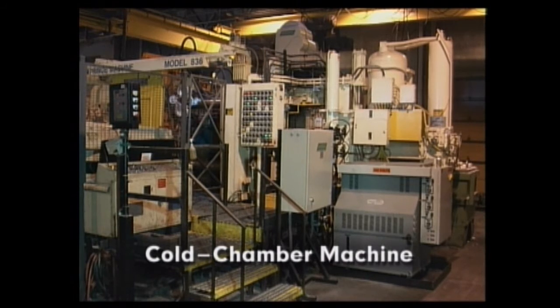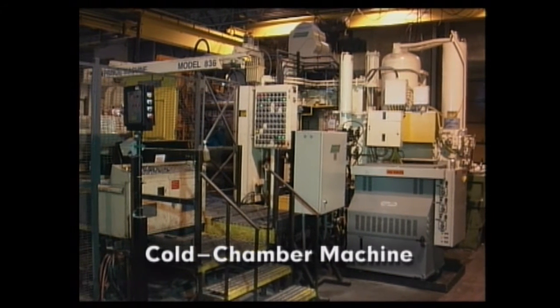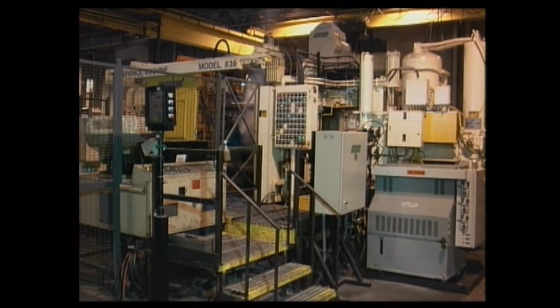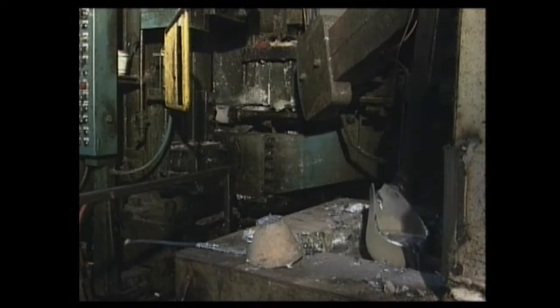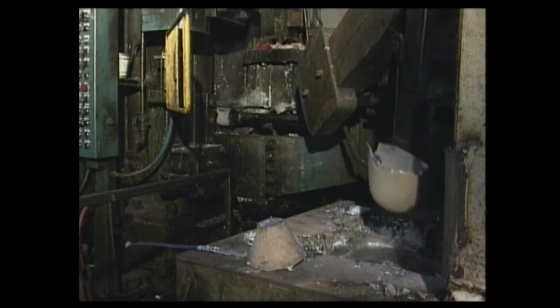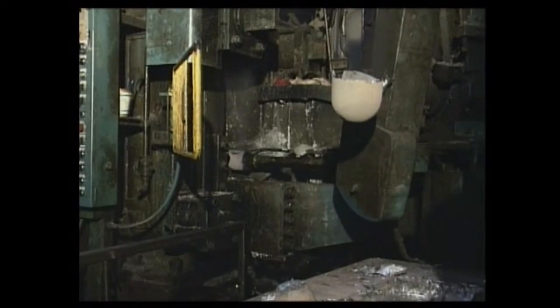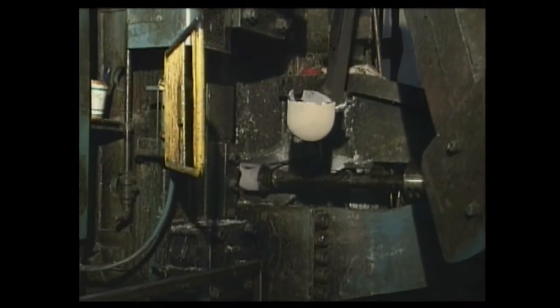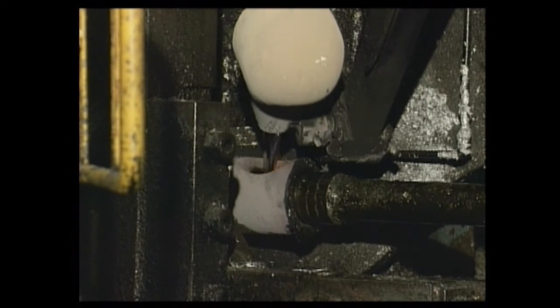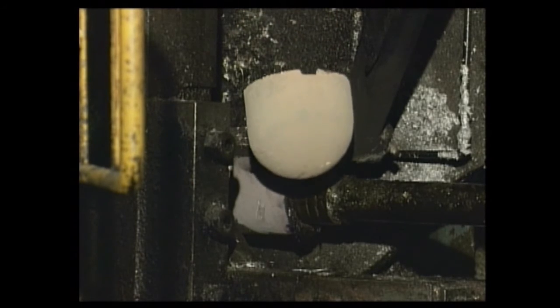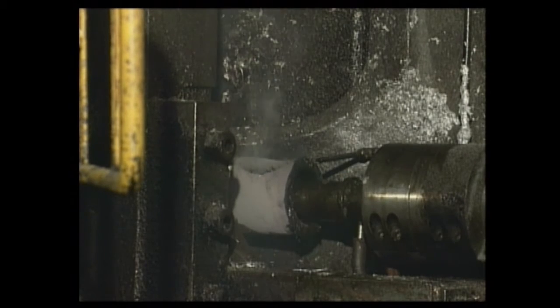The cold chamber machine is used primarily to die cast the aluminum, magnesium, and copper alloys. In the cold chamber machine, the charge is supplied by ladle or feed system from an external furnace source to a holding pot at the shot end of the machine. The feed system components are not submerged in the molten metal. The charge is poured ahead of the plunger tip through a pour hole in the shot sleeve. As the plunger advances, it closes the pour hole and drives the molten metal into the die.